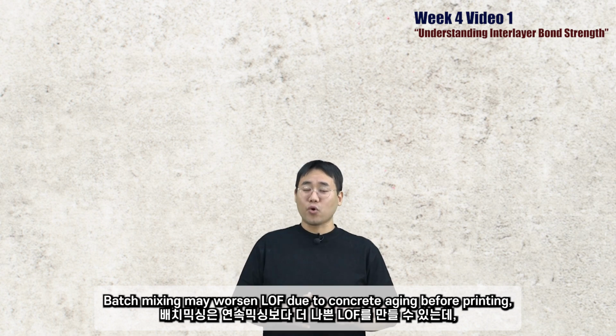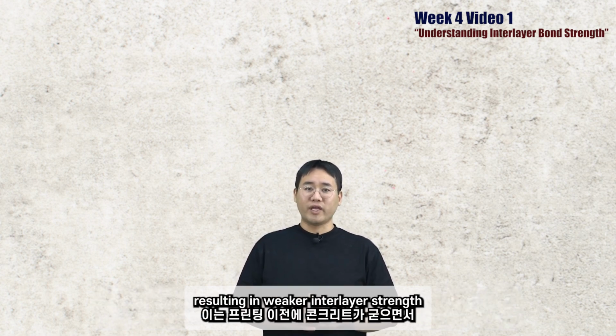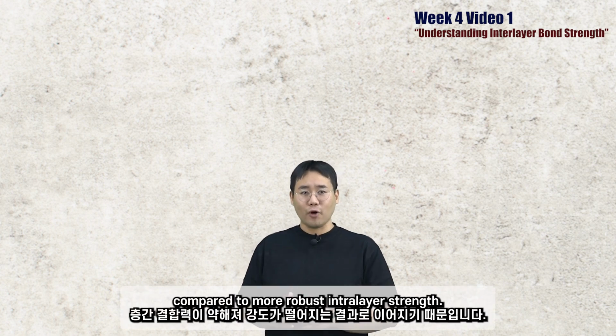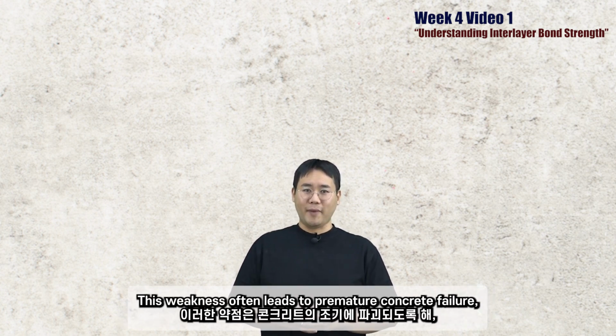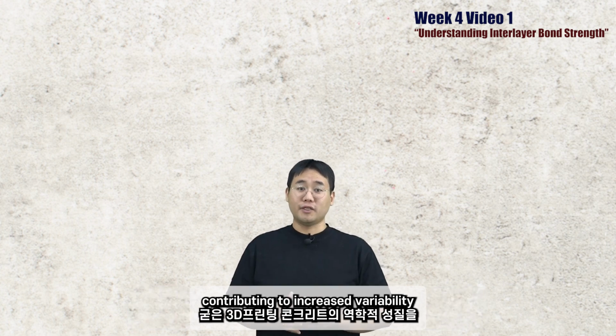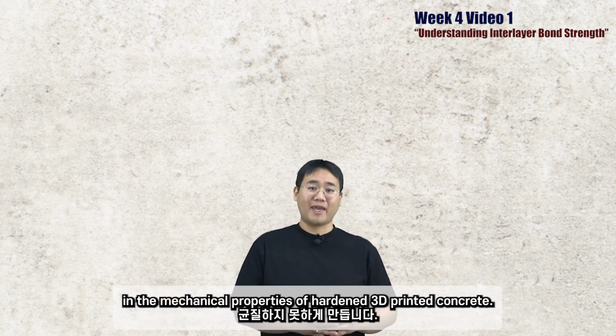Batch mixing may worsen lack of fusion due to concrete aging before printing, resulting in weaker interlayer strength compared to more robust intralayer strength. This weakness often leads to premature concrete failure, contributing to increased variability in the mechanical properties of hardened 3D printed concrete.